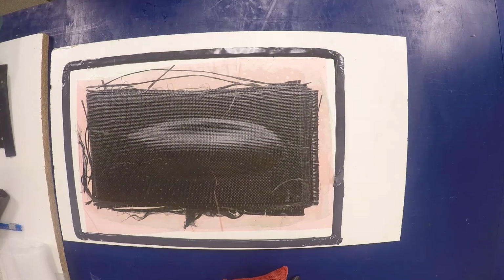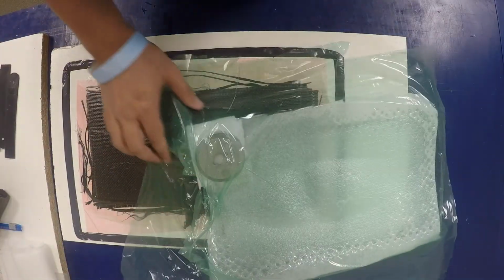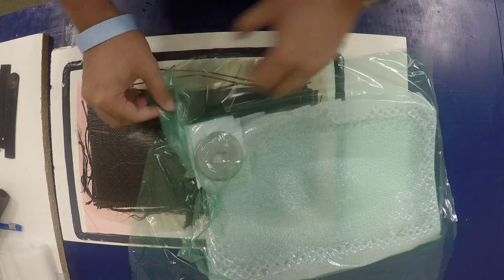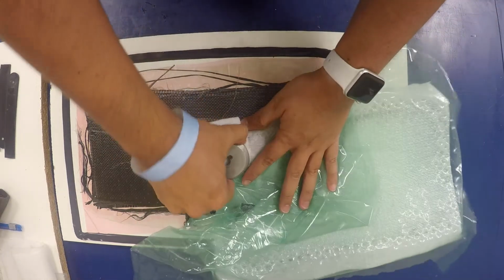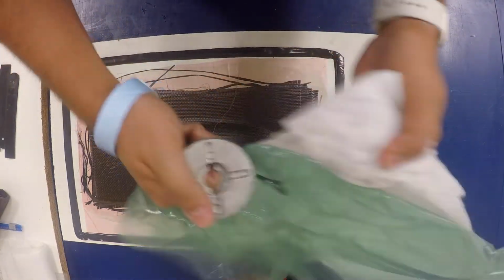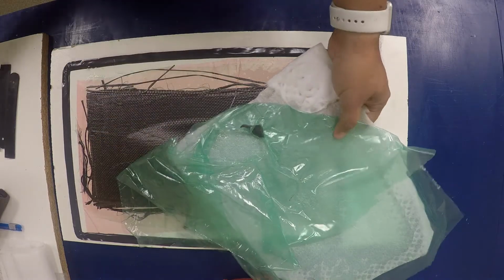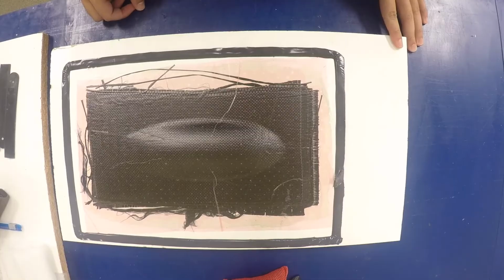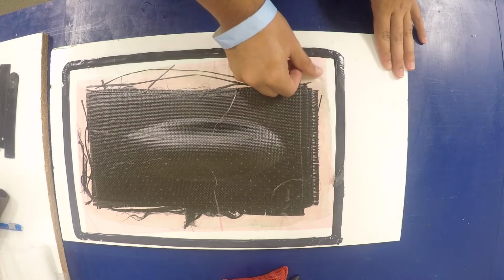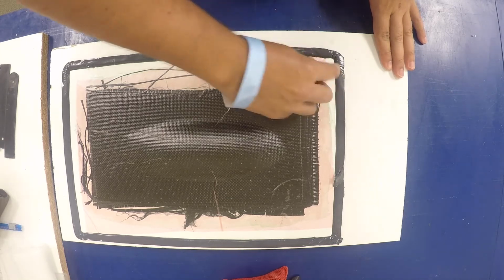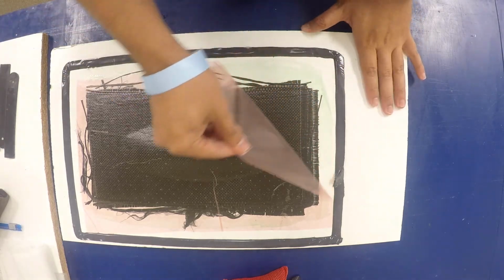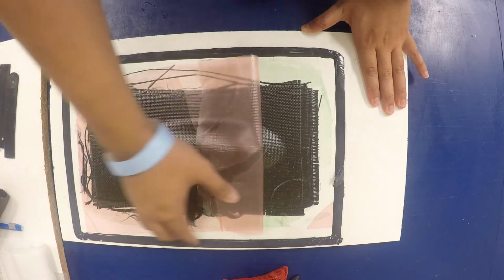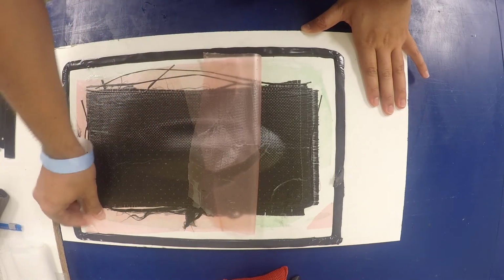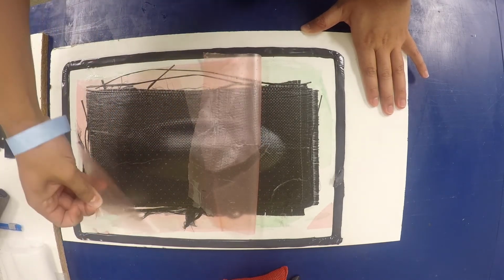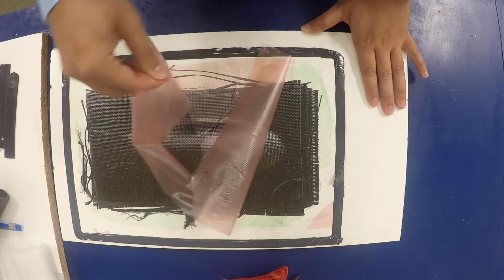Once you remove the vacuum bag, be extra careful to remember to remove the lower half of the vacuum port from your waste material before you dispose of them. Sometimes the release film will stay glued to the final product. If it stays behind, you can simply peel it off from the final product. Depending on the film, these can peel right off or begin to rip as you see here. It is easiest to remove the film as one, so if it begins to rip, try to begin from another corner.